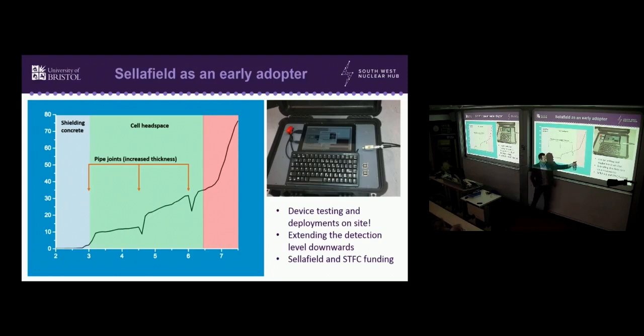Now, when we get to this red area, we're sitting between two tanks filled with this liquid effluent. And we're able to give a defined dose. And actually, because of some collimation we put on the device, it tells us roughly how full the tanks are, which is something that they just simply didn't know. Now, you can see we get some drops here. This is where the pipe that we've delivered it down has actually got double skin because they screw into each other. So the pipe thickness increases and it stops some of the gamma getting to the detector. But this is the type of data that they're recording now on a regular basis at Sellafield. And it works very, very well.